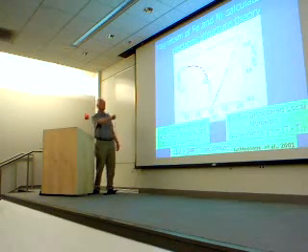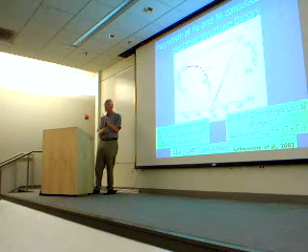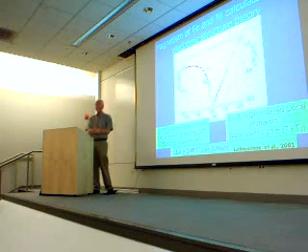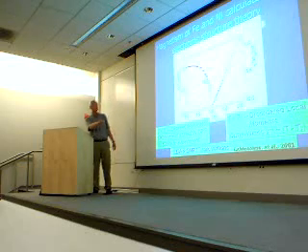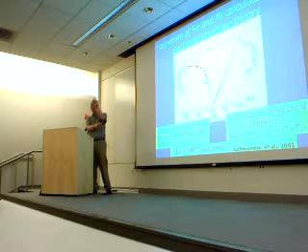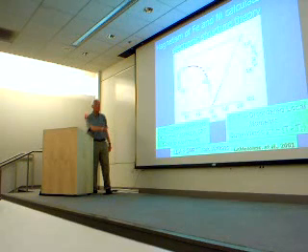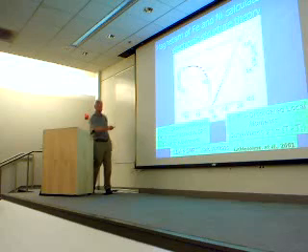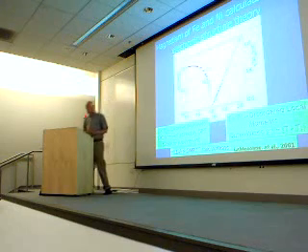And this is what comes out of calculations with a reasonable result for the magnitude of the susceptibility, which really is the magnitude of the local moments that are fluctuating. Okay, so starting from high temperature, you have a simple picture, just fluctuating moments, and the only thing about it is the value of the moments. That's the only thing you have to calculate. Go down in temperature, the moments become more correlated, and at some point they have the phase transition, and so this would be the approach coming from high temperature. And now the problem is to calculate the phase transition coming from high temperature.